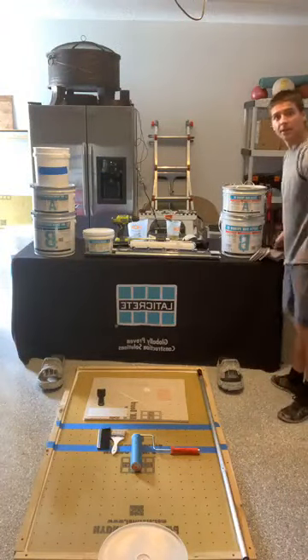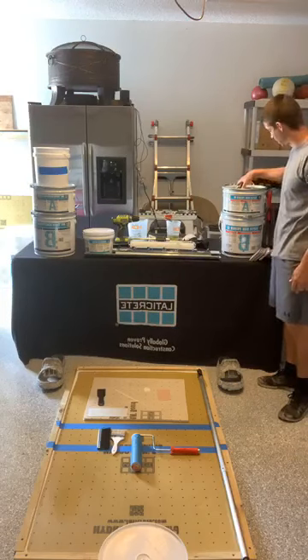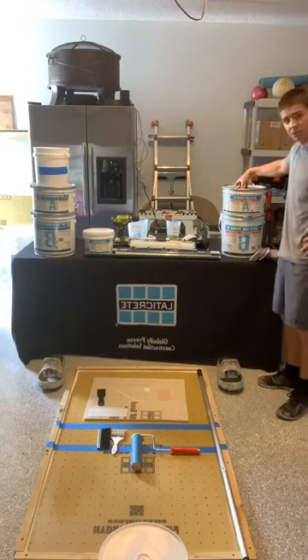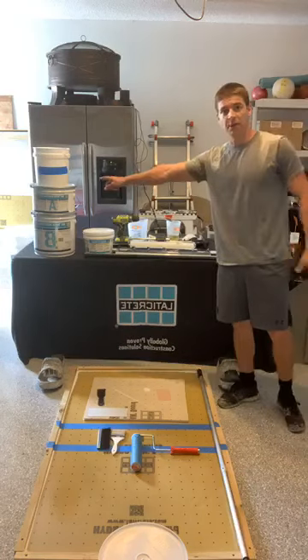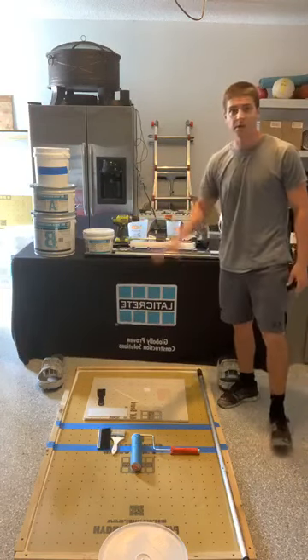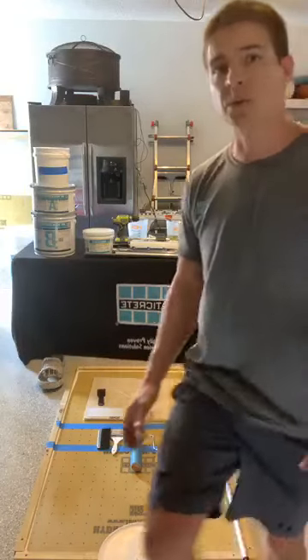Now, we're going to be covering Vapor Band, which is our fast cure moisture mitigation system, 2-component, and then our NXT Vapor Reduction, okay? They both meet ASTM F3010, which is very important. I use it as a standard for the industry. There are several different vapor barriers out there that tolerate different levels of moisture or different rates of permeability. The benchmark, if you're going to mitigate for moisture, the way I see it, is go big or go home. It peaks at 25 pounds and 100% relative humidity. That's what both of these products meet.